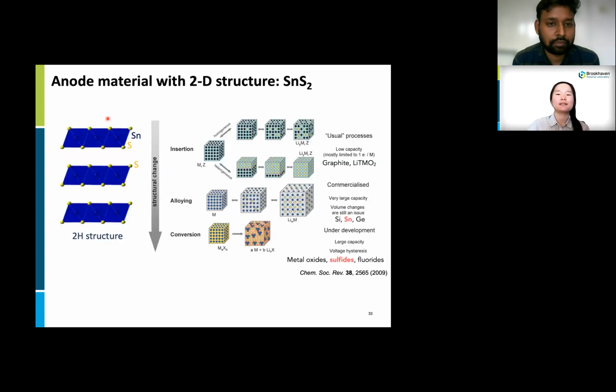Using this experimental approach, I explored tin sulfide materials. This tin sulfide is an interesting material because it has a layered structure, so lithium ions can be inserted by intercalation. Sulfide compounds are also available for a conversion reaction, which means we can store more lithium. And the reaction product from conversion, metallic tin, can also react with lithium by alloying. It means multiple working mechanisms can store lithium in a single material, and eventually tin sulfide has the potential to deliver much higher capacity.